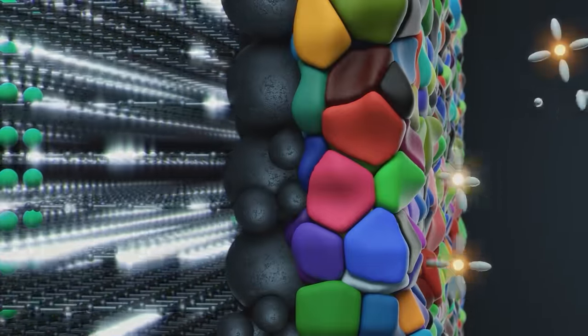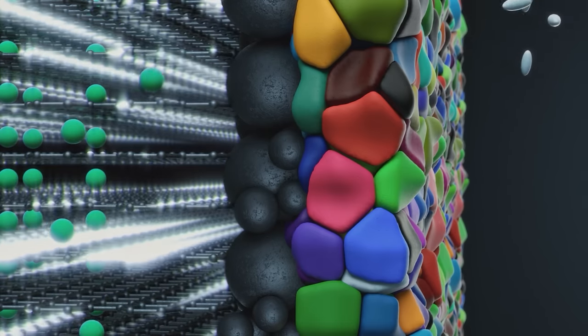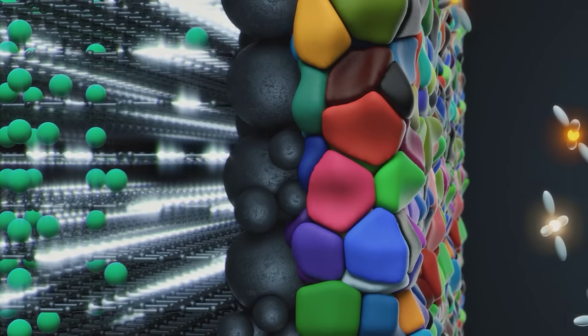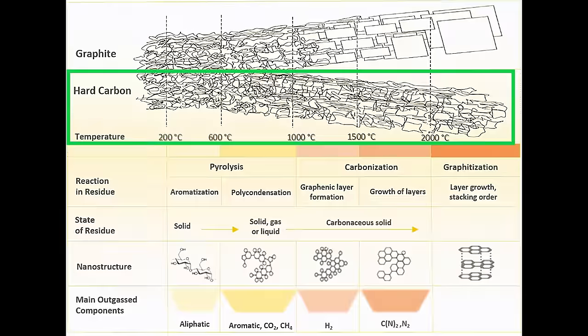But if you change to another solvent, sodium can actually intercalate into graphite. So never say sodium is too big to intercalate into graphite, because potassium has no problem intercalating into graphite. If you make potassium ion batteries, you still use graphite as the anode. So this is really the magic role of what we call the solvation and desolvation of ions from the electrolyte into the electrodes. Hard carbon is used for convenience; it is very easy to source. We call it hard carbon because it's basically disordered carbon, right?